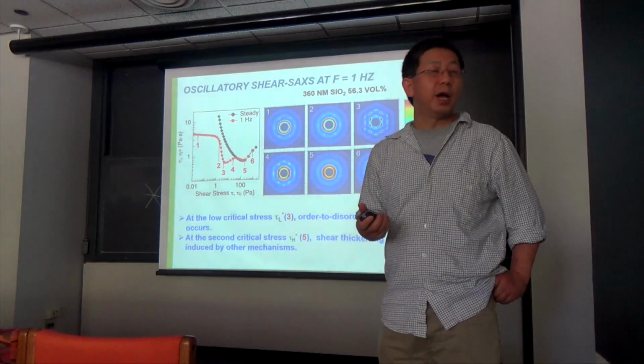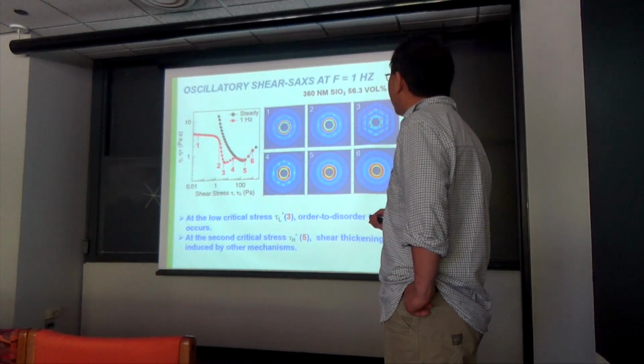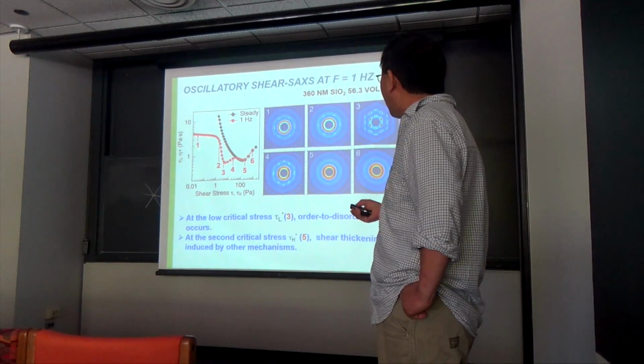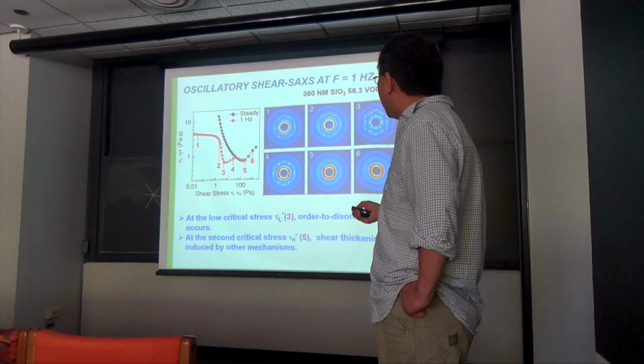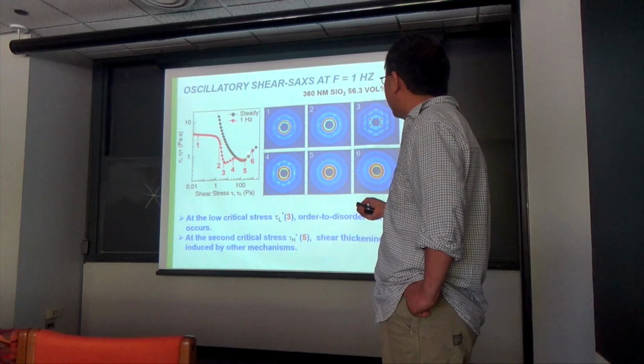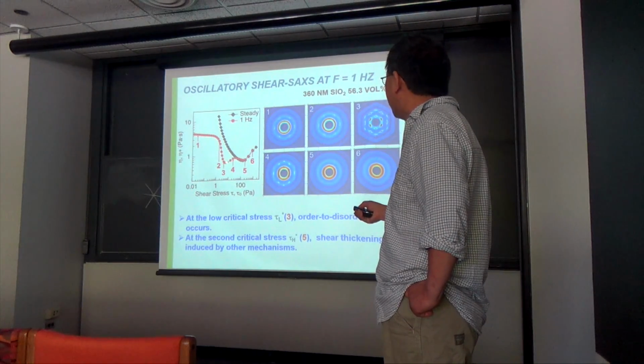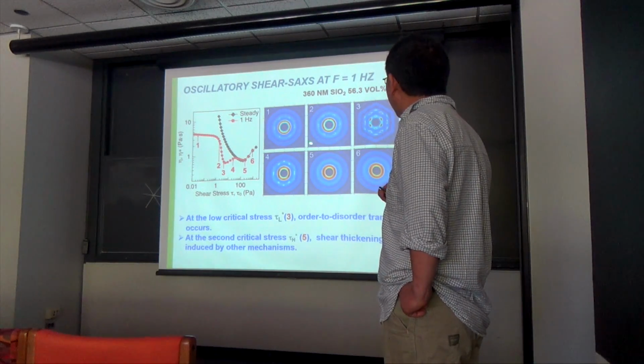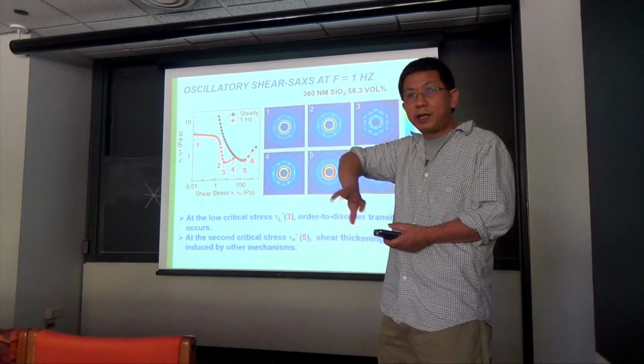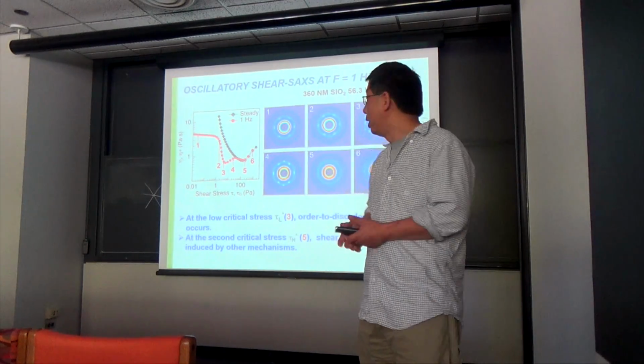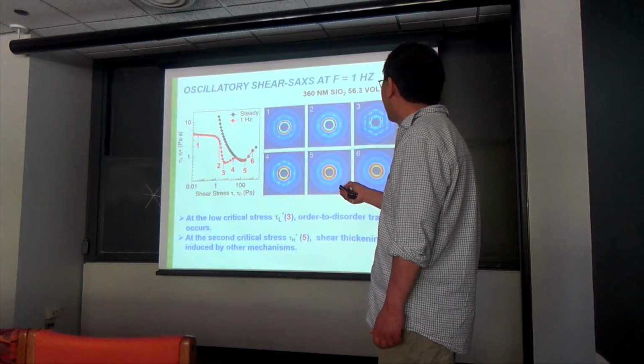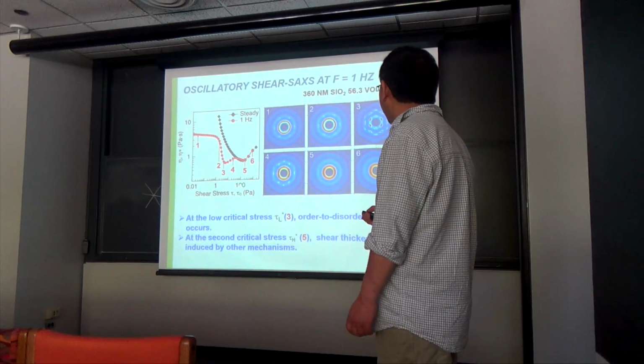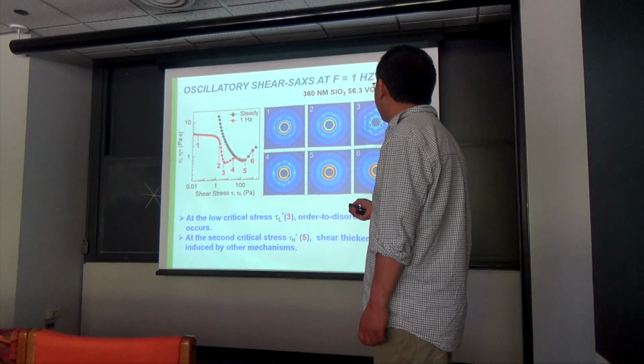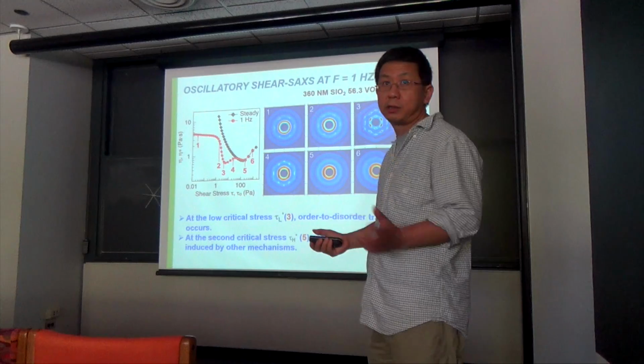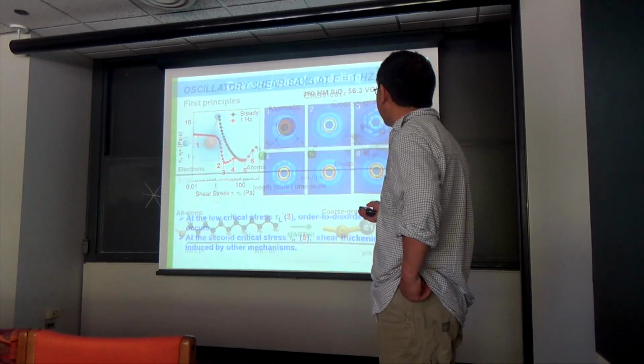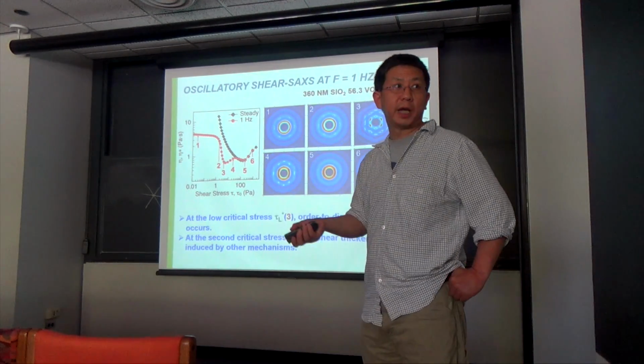Another thing is that these colloids are homemade, so the polydispersity is really, really small. If you don't have this control of the polydispersity, you see very different behavior. What happens is that during oscillatory shear, you see two-step shear thinning and shear thickening behavior. The first step of the shear thinning, shear thickening behavior, the critical stress here at number 3, actually corresponds to the order-disorder transition. Essentially, when you have oscillatory shear, it is likely to form these highly ordered layer structures, and that dramatically decreases the viscosity. But if you have a steady shear, it bypasses this order-disorder transition completely. And so the critical shear thickening at this number 5 point is not associated with the order-disorder transition. So for the first time, we are able to distinguish order-disorder transition-induced shear thickening from other mechanism-induced shear thickening.